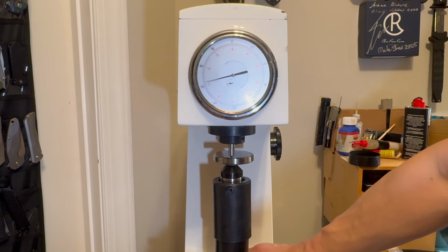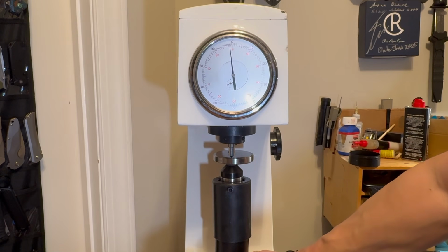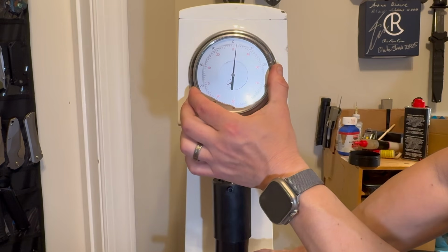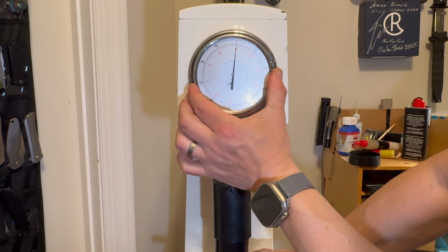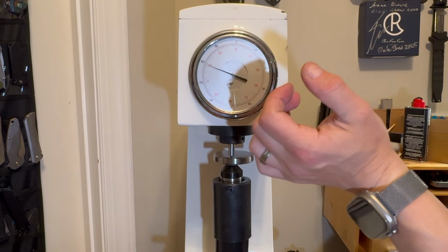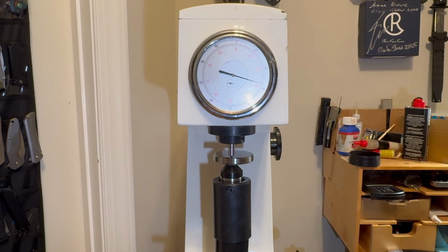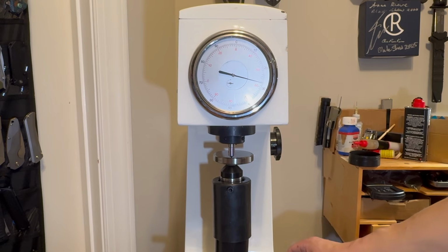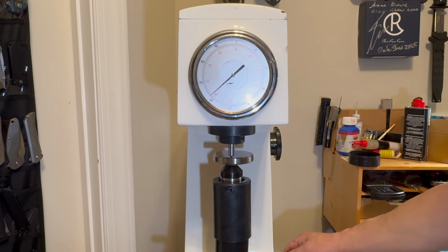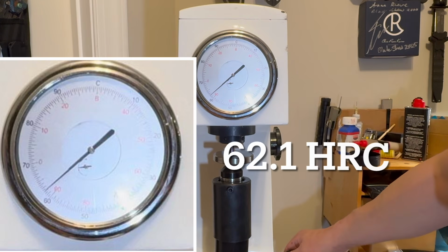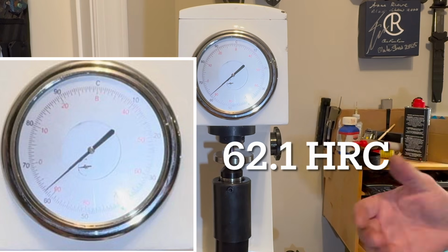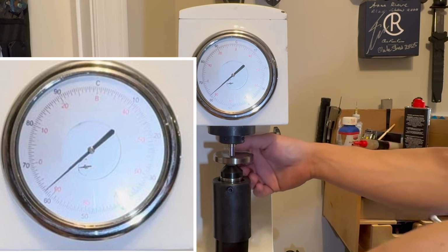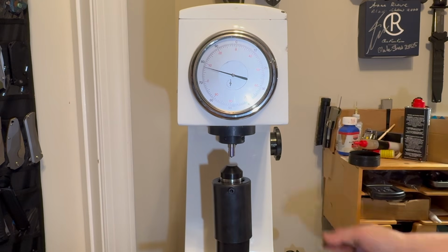Appreciate that. In my tests, I use industry standard equipment. Now, that doesn't mean that this is an industry standard test, because such tests would require a sample of 5 blades out of every batch. So what I'm trying to say is yours can be harder or softer than mine. The good news is that the heat treatment cycle developed by Paul Bos for Buck is extremely consistent. And I'm reading 62.1, which means I'm really well within the calibration.